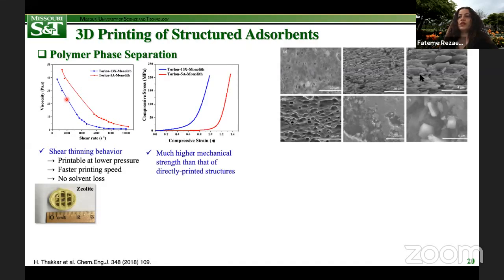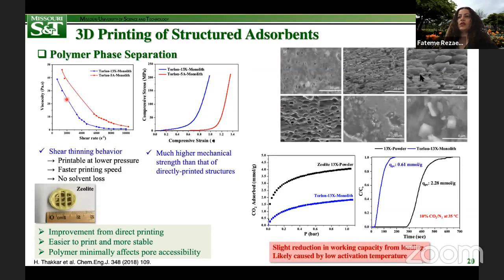Another noticeable finding was much higher compressive strength for polymer sorbent monoliths than that of self-standing monoliths prepared by direct printing. Other advantages of this technique include improvement from direct printing, easier to print, more stable, and the polymer phase minimally affecting pore accessibility. The printing strategy reported here can be easily expanded to other organic-inorganic composite materials with different polymers and inorganic particles. Despite this, an associated drawback that may limit the applicability of this technique relative to other materials is low adsorbent loading, as stated before, up to 60 weight% compared to those obtained from other methods.